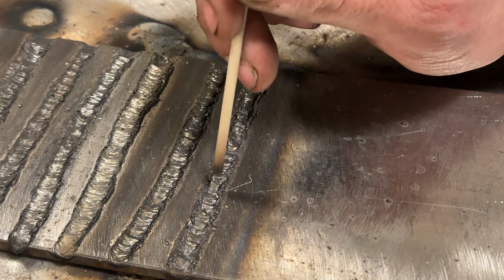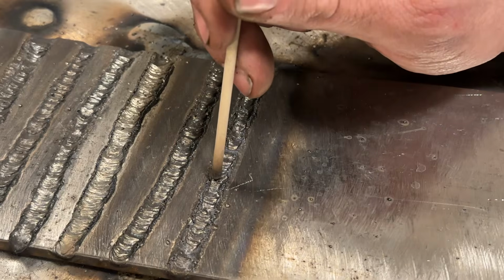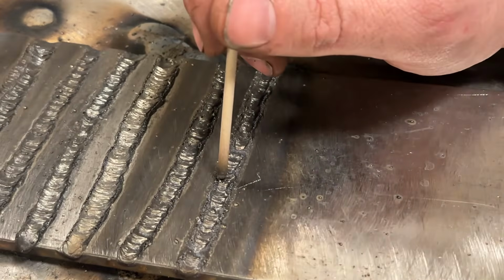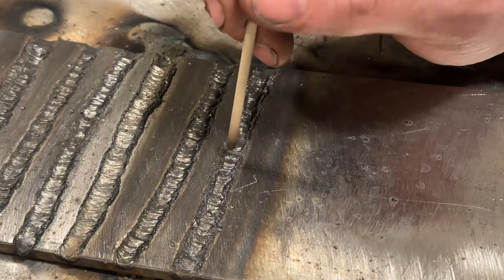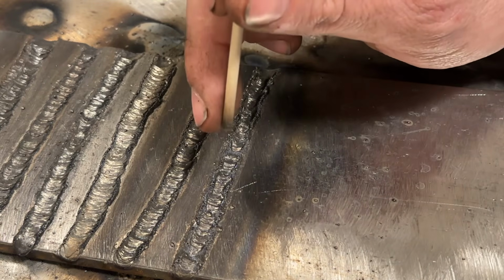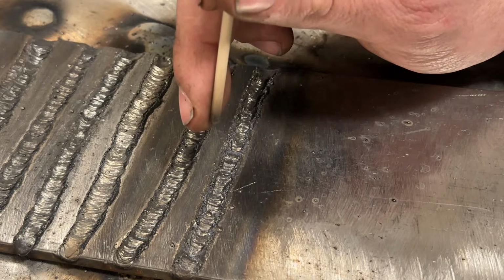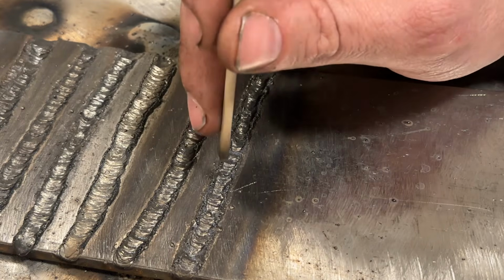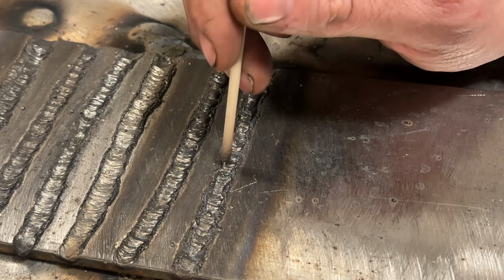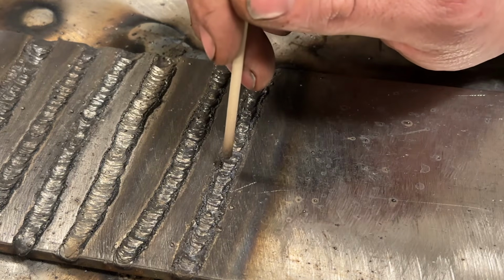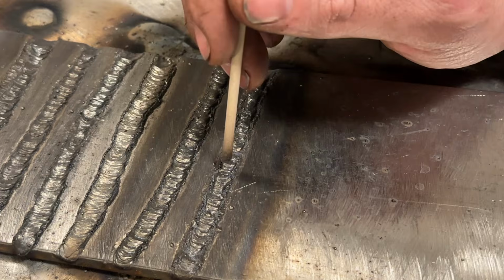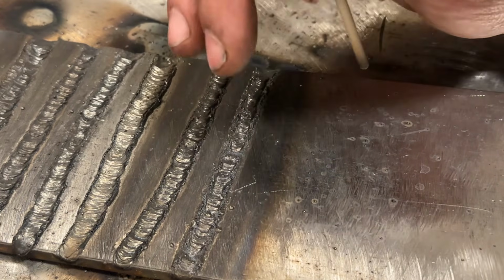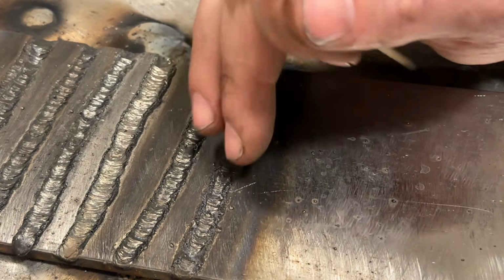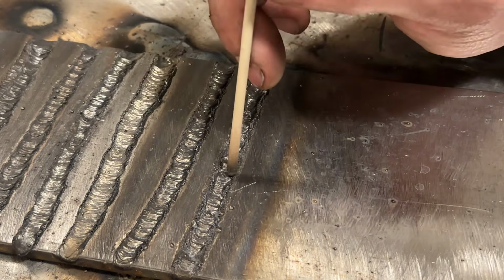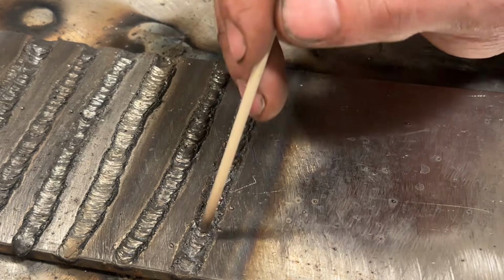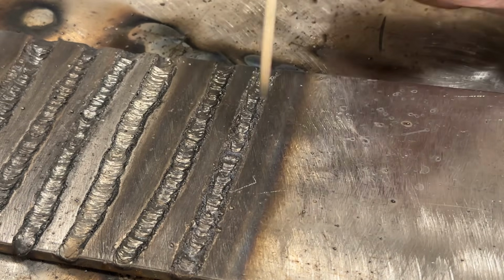Not to mention, as you bring this rod off this plate, every half a millimeter adds more voltage, and more voltage means more heat input, which then makes more of the tip of the rod melt off, and it increases the heat. You want to keep your arc gap tight, because the longer the arc is, the further the molten balls are going to fall, the more the heat is in the arc area. You want to keep it under control. Hopefully that was clear as far as the long arc.